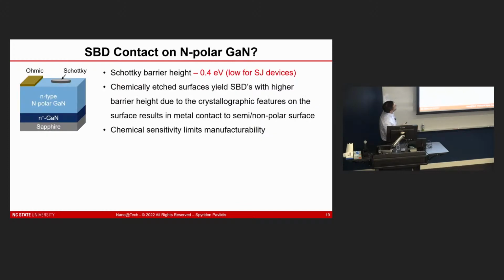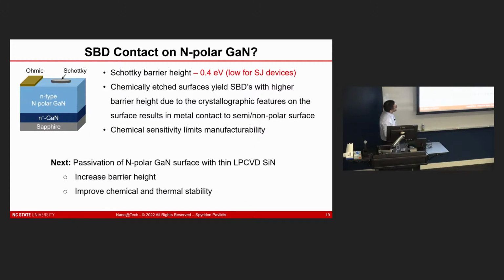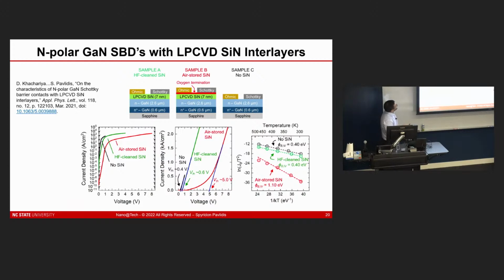So we've shown now that you can make a high-quality Schottky contact if you control the surface and keep it clean. We demonstrated relevant doping levels, but also showed that there's a low barrier there that could lead to leaky currents. And so we want to increase that barrier height and think about ways to improve chemical and thermal stability. One of the things that we leverage for this is making a thin silicon nitride interlayer, and we have specifically been doing this with low pressure chemical vapor deposition. This was another study that we published where we deposited these LPCVD layers, relatively thin at 7 nanometers, and then put down our Schottky contacts on top.